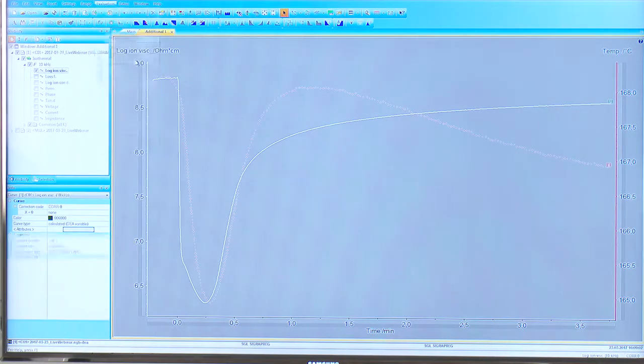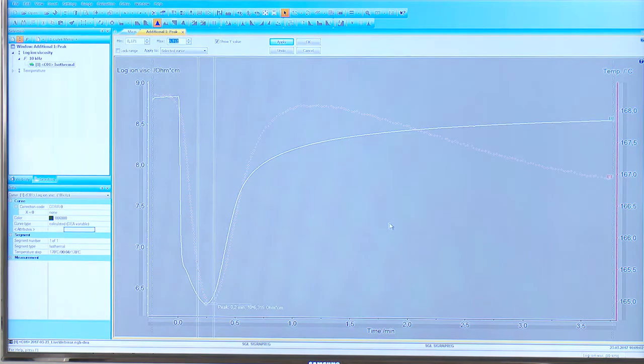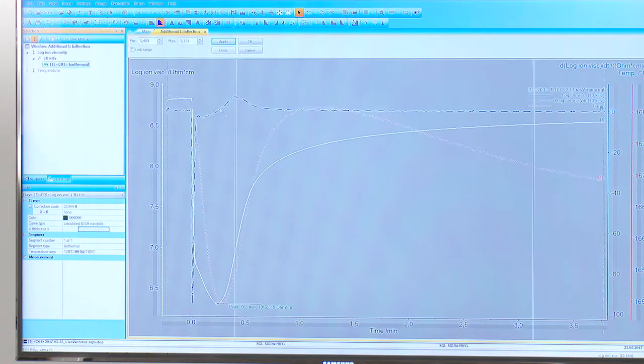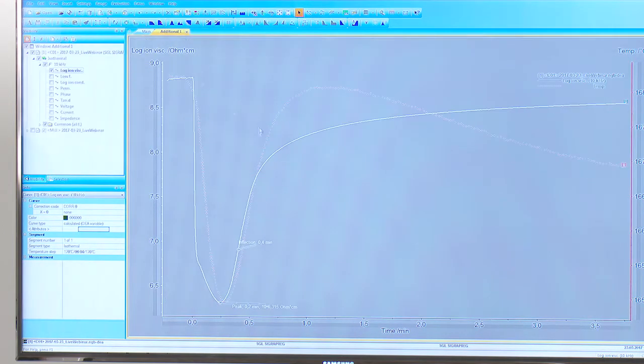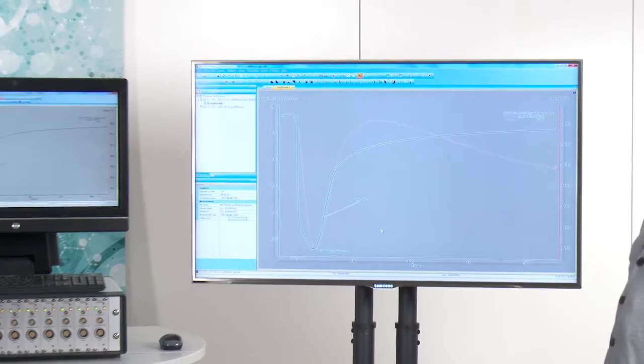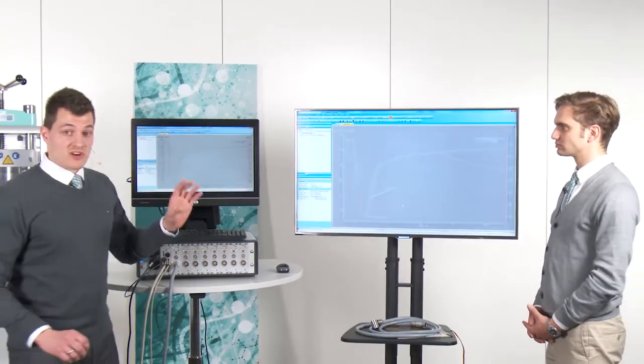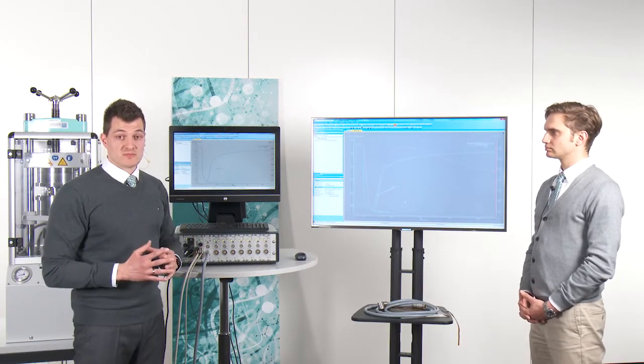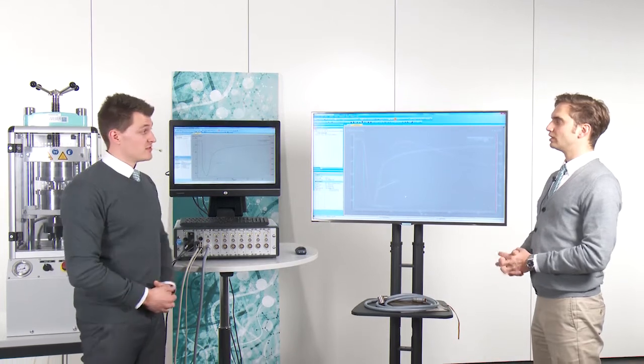Now we will have a look at the most interesting points of this measurement. The first very interesting point is the minimum in viscosity, because this is the point where processing is much easier than, for example, in a pre-cured state. So it's a very low viscous material at this point. And the second point we can evaluate is the point of inflection in ion viscosity. You can see it here as a peak in the derivative of the ion viscosity. So I will change the time unit to seconds. The point of inflection gives us the information about the reaching of the gel point of this material. So this point correlates very, very well to the gel point you know from rheology measurements as a crossover between storage and loss modulus.